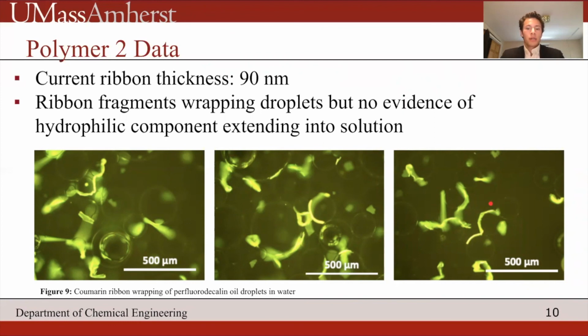And we're also seeing that the ribbons are rather fragile and break apart in solution. So as you can see on this rightmost image, this ribbon is not very long. And so this may be because of low ribbon thickness or because of the decross-linking component that occurs at 254 nanometers, which is what we are currently working on at this stage of my thesis.